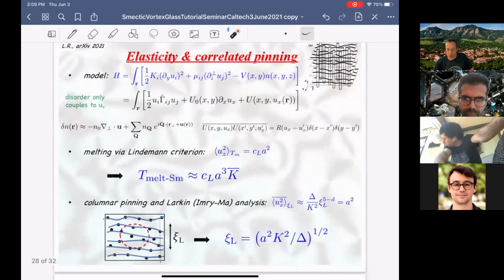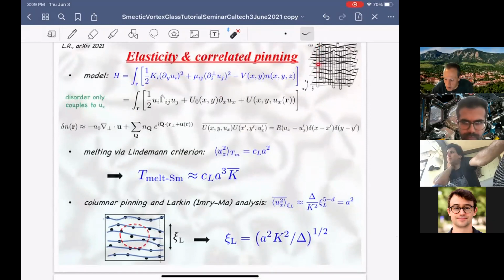So let me try to show you the model that describes this. It's very simple. You start out with some elasticity. It's biaxial elasticity because there are really 3 axes here, and they're distinct axes. And then you have a pinning potential. Unlike a single pin, this potential is a random potential that acts on the vortex density n, and it acts everywhere. It turns out you can rewrite this model in terms of some effective elasticity characterized by a kernel gamma. And then there's a random field-like term. If you think of this as an XY model, there's a random field-like term that couples to the UX, but not the UZ degree of freedom. That's easy to understand. There's no point of distorting in the Z direction because there's no pinning in the Z direction. So UZ is really, roughly speaking, 0, at least at 0 temperature.